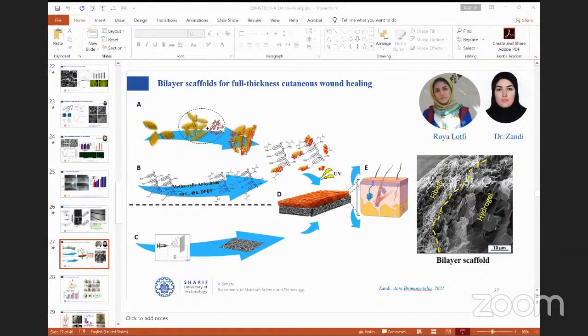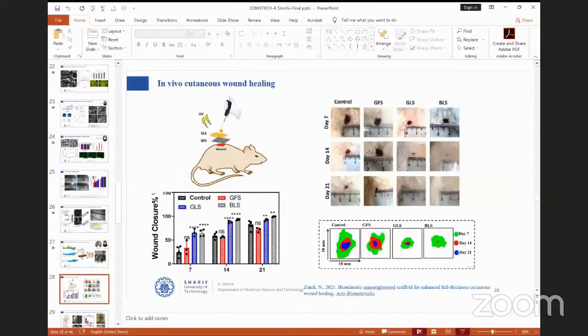The SEM picture shows our system, down and top side. Both are porous, but with two different functions. Then we used this material for in vivo examination on mice. As you see here, we induce a very deep injury inside the skin of the mice, and add the bilayer on the top and monitor the development of the wound healing process.